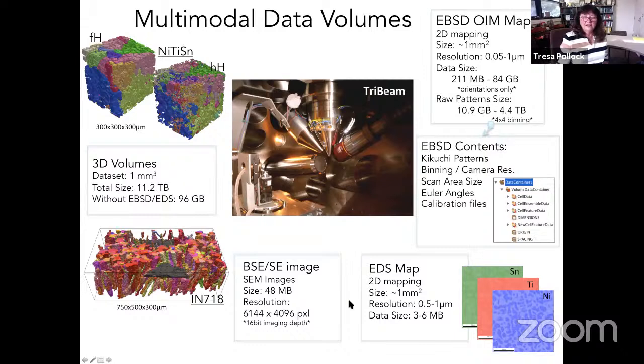Now, as I said, we're gathering a lot of data here, and it turns out additive manufacturing on many fronts is really a data problem. And so what you can see here is that you gather these different modalities of data, and there are big chunks of data that one stores. And the biggest part of that is the electron backscattered patterns that give you the grain orientations. Now, another challenge with regard to using different sorts of detectors is that they all have different distortions. And so one has to find corrections and approaches to merging the data into these 3D data sets.